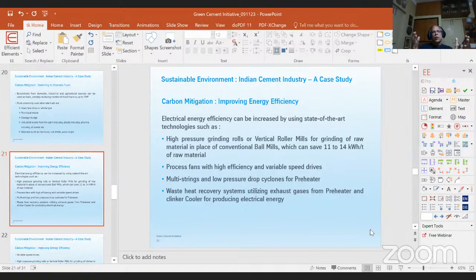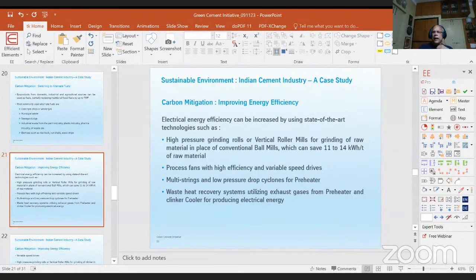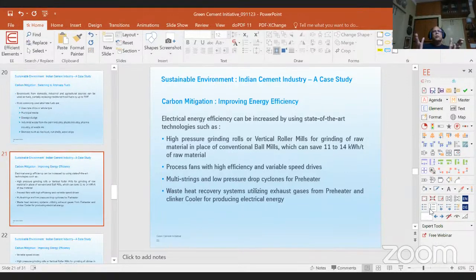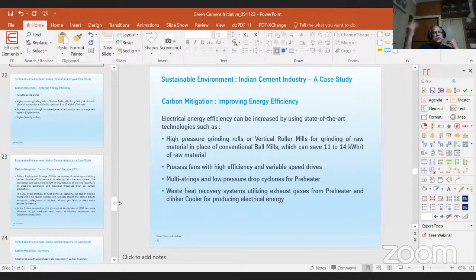Then we have multi-string and low pressure drop cyclones for preheater. That means you are designing cement plant machinery in such a way that you require low power. Your power consumption is reduced. Then you have waste heat recovery systems utilizing exhaust gases from the preheater. Typically, if you go by the thumb rule, I think it's mandatory now. All the greenfield plants need to go with a WHR system, with waste heat recovery, and instead of allowing the heat to be thrown into the environment, you recycle it and generate power and become sustainable. So today, for a million ton plant, about 3,000 tons per day, you can expect to generate about 3.5 to 3.7 megawatts of electrical energy, which you can utilize yourself and reduce the grid consumption.